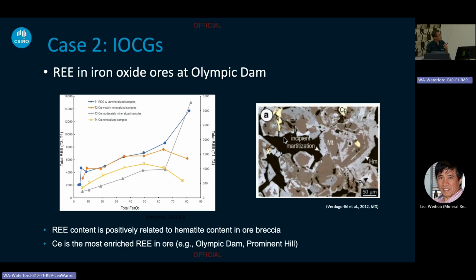So case study number 2 is about IOCGs. This is one work I did before, taking iron oxide ore as an example. The iron oxide copper gold deposits are often massive iron oxide ore bodies where you see magnetite and hematite everywhere. And one small specific phenomenon we observed is the REE in the iron oxide ores. This is data reported by the PhD student: the total content of iron and the total content of REE. So they are well correlated.